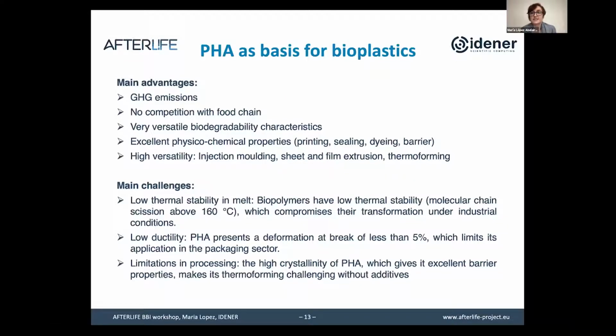Also, PHA is a brittle polymer, so it has a very low ductility. This limits the application in the flexible packaging sector. On the other hand, for processing with thermoforming, we need to add some additives or other polymers to reduce the crystallinity of the PHA, and this way increase the processability of the polymer.